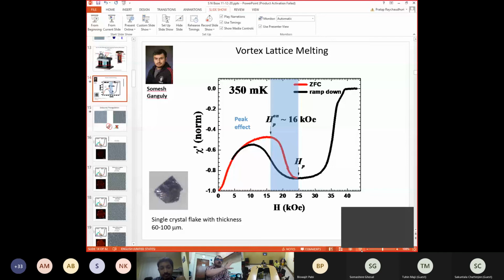So how do you know? You start from a solid, you cross the boundary of the phase transition, and it remains a solid. But then you apply a small magnetic field pulse and it immediately becomes amorphous. And you know that it was a superheated phase. In fact, this is how we have shown that this is a first order phase transition.